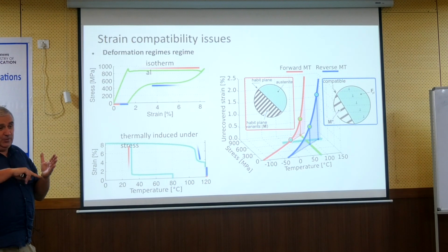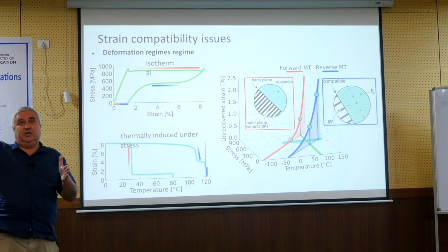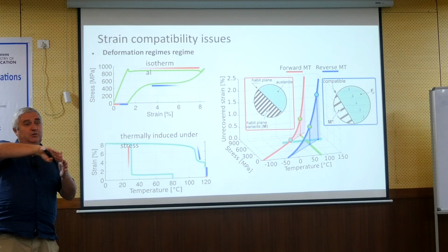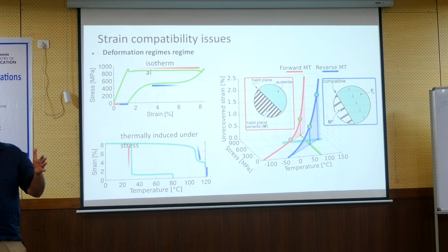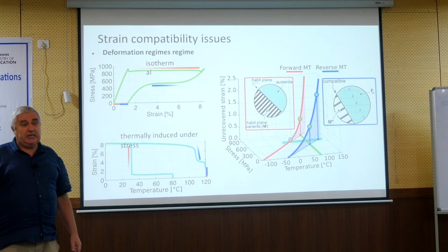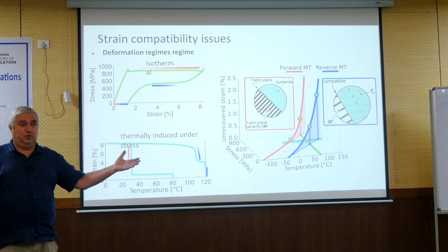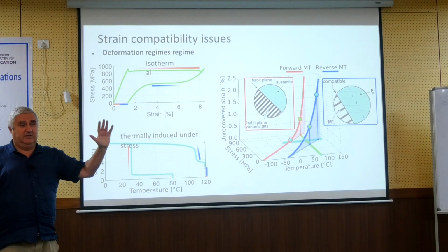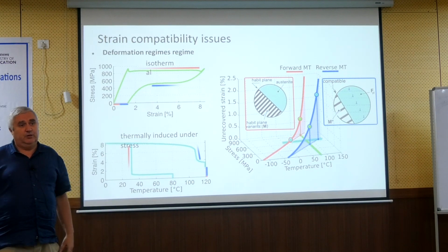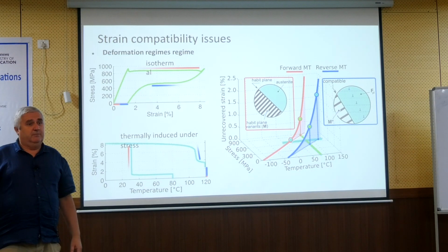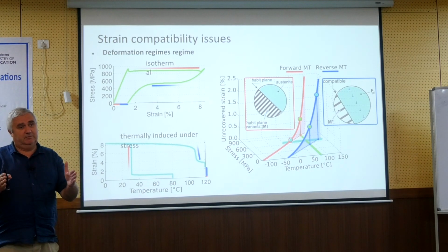After 10 cycles, like I said, there is this stabilization. So this knee over here, for most alloys, is around 10 cycles. In the first 10 cycles it increases quickly, and then it goes slowly. So we can say that the unrecovered state which accumulates every cycle, after 10 or 15 cycles, that amount will be much less. So it's a good idea, before you use the wire for a superelastic application, to make 10 cycles exactly with the strains you want to use, and no more. If you do more, it's maybe redundant, but same type, same strain.